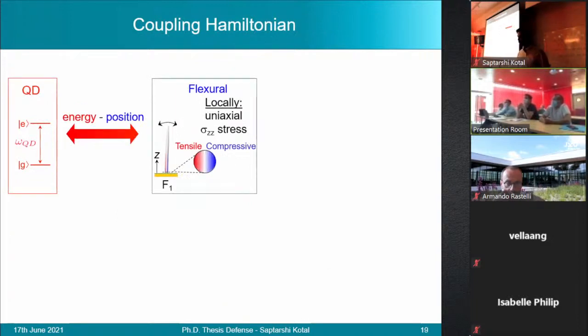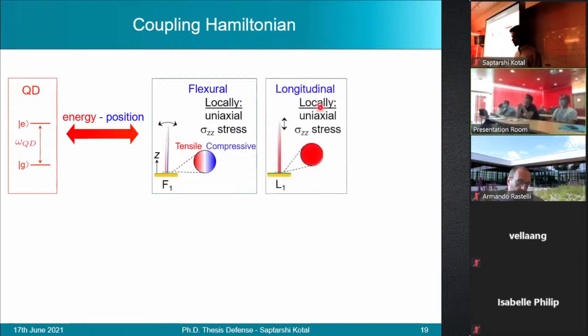To address this question, we implement the following theoretical model. We consider a quantum dot to be a two-level system, which is coupled to the vibration modes of the nanowire, which we treat as a harmonic oscillator. Then we divide all the vibration modes into three broad groups. First, we have the flexural modes, where the nanowire flexes from side to side, generating a stress gradient across the cross section at the level of the quantum dot. Then we have the longitudinal modes, where the nanowire stretches and contracts vertically. This results in a stress which is uniform across the cross section.